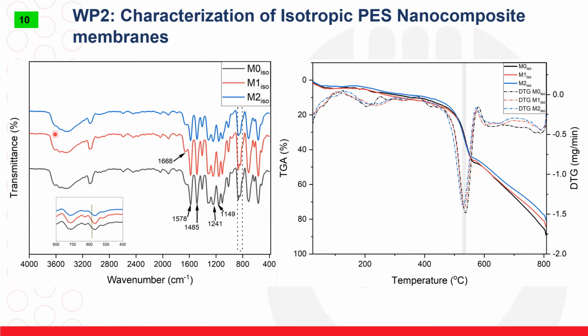FTIR characterization revealed all functional groups typical for polyether sulfone. And the addition of molybdenum disulfide in polyether sulfone did not affect much the positions of the functional groups. Also, using thermogravimetric analysis, we realized that the decomposition temperature of polyether sulfone was not much altered.